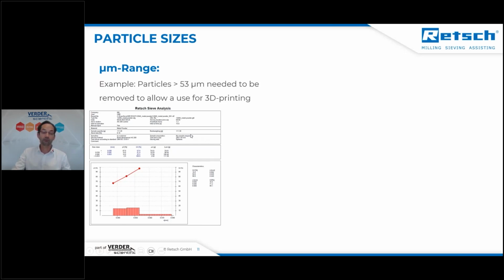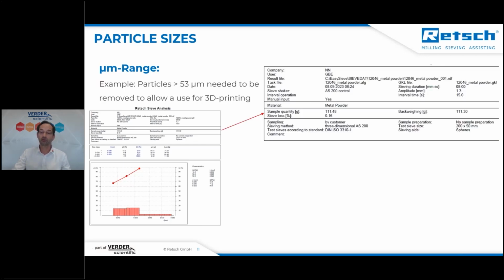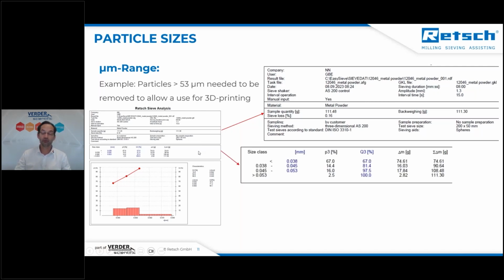This now shows a complete protocol of the sieve analysis. We've got detailed information about the complete process, like the information of the material, the kind of sieving process, the machine that has been used, and lots of other information. Most important, you get a tabular result at the end, where you can see how much of your particles are smaller than a certain size. In this example, 67% of the whole powder is smaller than 38 micron. And on the other hand, you see here, for example, that 2.5% of this powder is bigger than 53 micrometers.